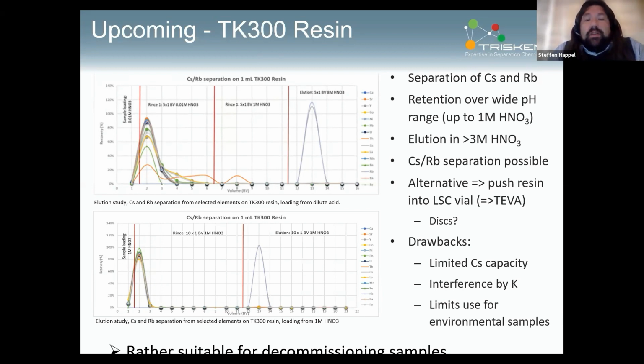Direct load of an acidified water sample, just concentrate on the cartridge, rinse off interferences with 1 molar nitric acid, and then elute the cesium and rubidium with nitric acid. If you need for your application to separate both, it's possible too at about 3 molar nitric acid. A bit cleaner separation is obtained when you directly load from 1 molar nitric acid and then elute in 8 molar nitric acid. So generally you load from more or less dilute nitric or hydrochloric acid, then elute in quite highly concentrated acid, which is in itself a bit unfortunate. It's usually not what we are looking for.